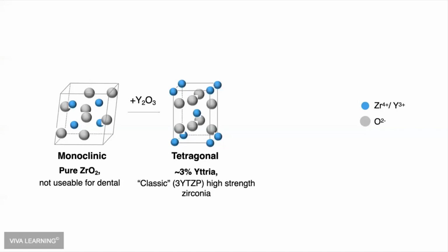And when we have yttria, we end up turning this zirconia into what's called tetragonal. It's a phase of the zirconia, and when we add 3%, we end up getting more tetragonal. Tetragonal is a very strong form of zirconia, and it's able to essentially transform if there's cracks that are starting to form. This tetragonal component of the zirconia acts almost like a sponge, where it moves and fuses and essentially closes off the crack propagation and keeps those cracks at a very small microscopic level.